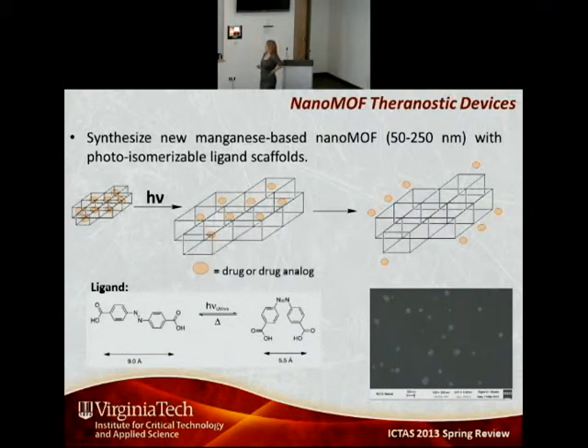Metal-organic frameworks are very porous, so you can incorporate the drug into the framework. Then upon irradiation, you start, in a sense, wiggling these ligands. So there is a shape shifting within the material, and then the material either breaks or the pore size changes, and the drug gets released.